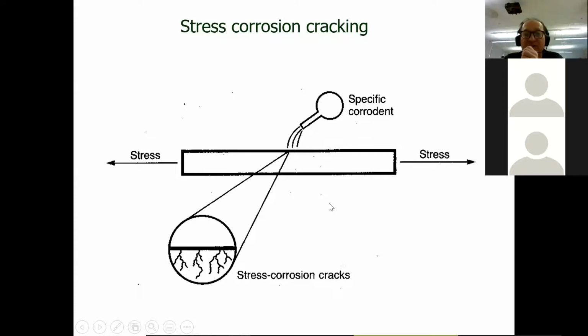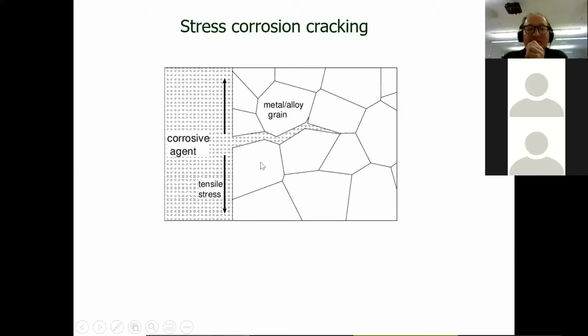So if you look under the microscope and you're stressing the sample and you have corrosion, you'll start to see what looks like a Christmas tree effect or forked lightning. These cracks are going everywhere from the surface. These propagate. And in particular, what happens is the crack goes down the grain boundaries like this. So here's the grain. You've seen these grains before. All materials have grains in them. And the aggressive environment, or the crack, just propagates between the grains usually, down there, which is the path of least resistance. And the hydrogen I just mentioned goes down this crack as well.